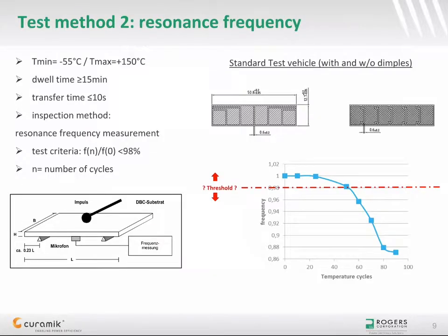But a non-destructive method is based on the measurement of the resonance frequency. A test setup is shown in this slide on bottom left. A light knock on the top side will induce a vibration in the ceramic substrate that is captured by a microphone on the opposite side. For the specific test vehicle shown on top right, it has been observed that the resonance frequency decreases as cracks appear and grow in the ceramic. This decrease in frequency can be plotted as a function of the number of temperature cycles, as shown here on bottom right. However, this doesn't answer the question when the substrate has failed or has reached end of life.